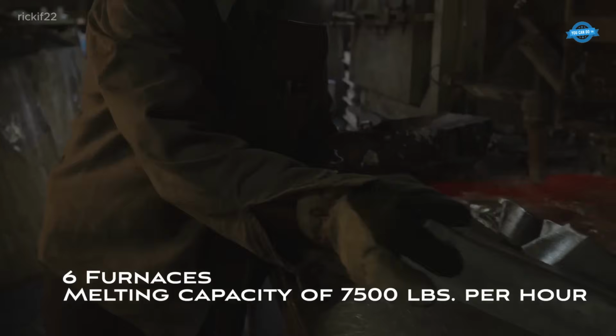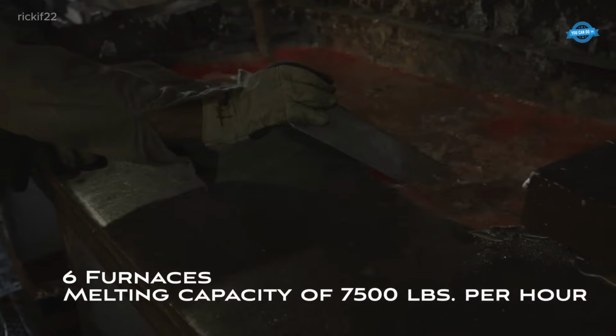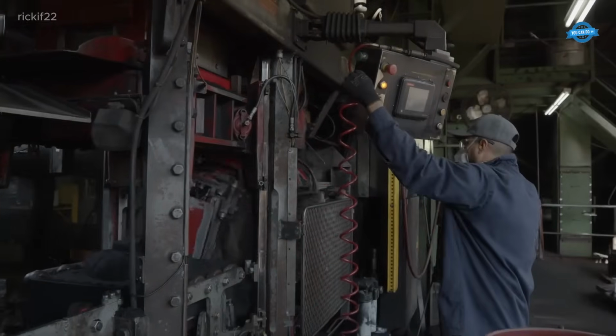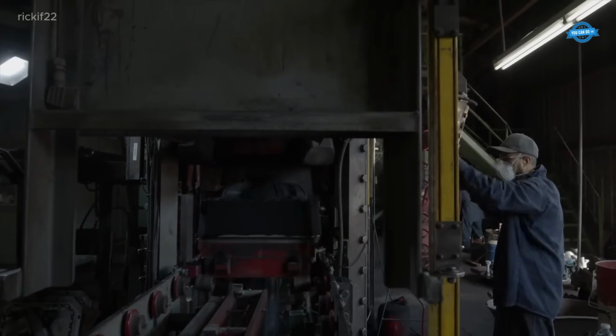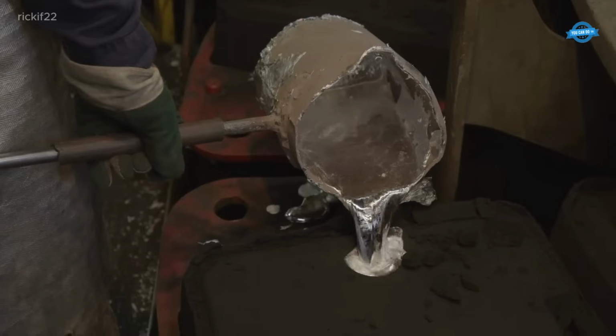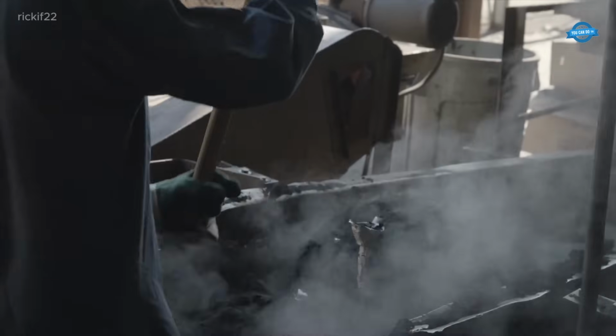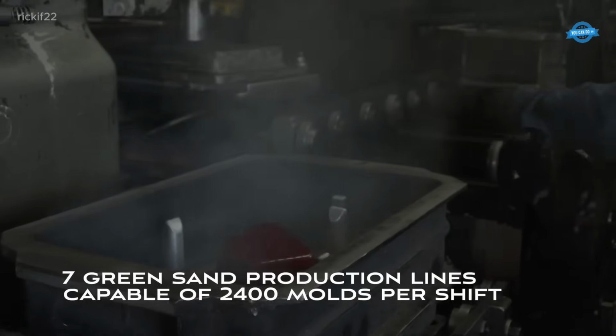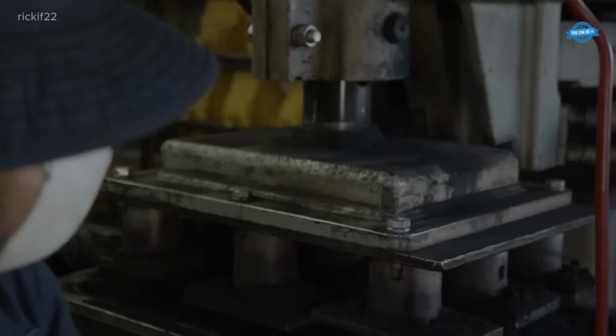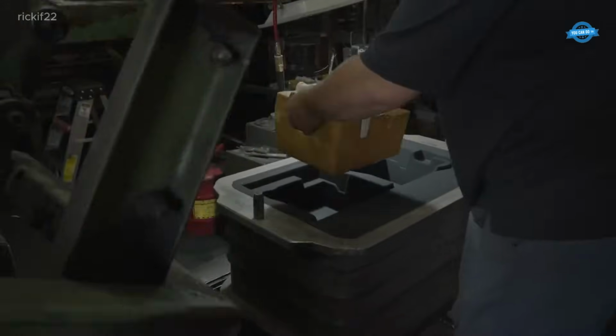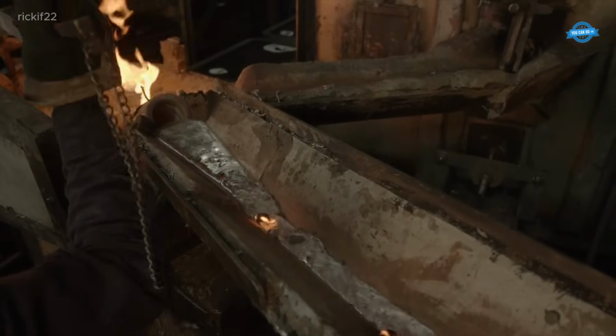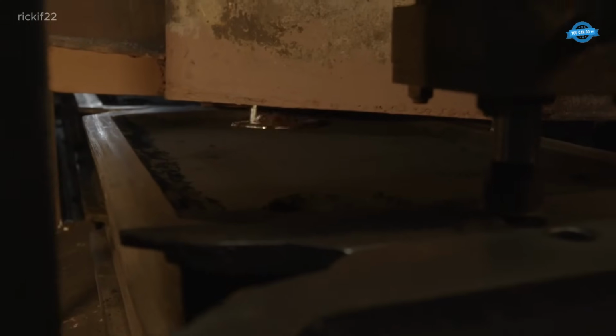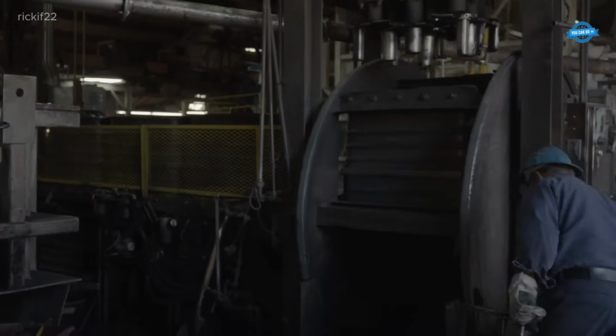After casting, the aluminum parts are processed through a thermal sand reclamation system, ensuring 100% recycled sand, making the process environmentally friendly and efficient. With 6 furnaces capable of melting up to 7,500 pounds per hour, we ensure a stable and reliable supply of molten metal for casting. The shop also features an automated match plate molding line and 7 green sand production lines with the capacity to produce 2,400 molds per shift.